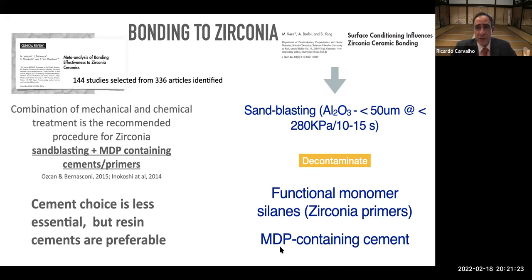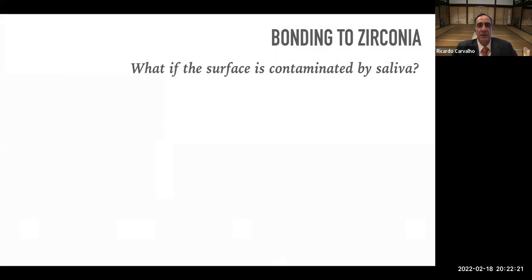But again, do not trust this chemical adhesion as your main retention mechanism. Your crown needs to be fully well prepared. We have to follow all the prosthodontic requirements for the stabilization of the crown, retention, etc. And we just try to get additional bond to favor the retention and also the sealing. However, we know that once the primer itself is really important because it does promote bonding to the ceramic, having MDP in your cement is not necessarily the most crucial. So the cement choice is less essential, but of course, resin cements will always be preferred. And if you have one containing MDP, there is some evidence that supports additional longevity when you do that.